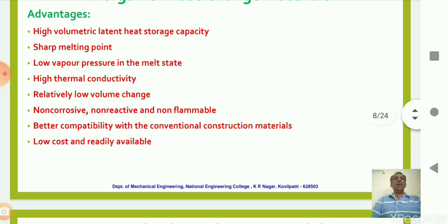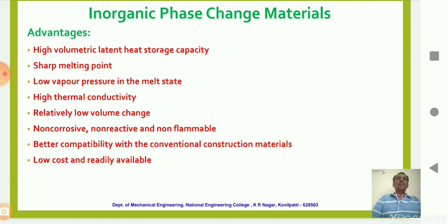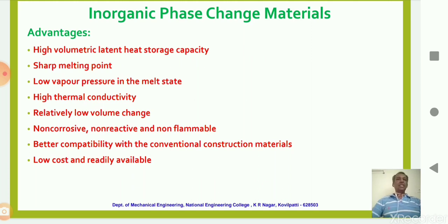Advantages of inorganic phase change materials include: high volumetric latent heat storage (high latent heat per unit volume); sharp melting temperature; low vapor pressure in the molten state; high thermal conductivity; low volume change upon heating; non-corrosive, non-reactive, and non-flammable properties; good physical and chemical properties; compatibility with conventional construction materials; and low cost with ready availability.